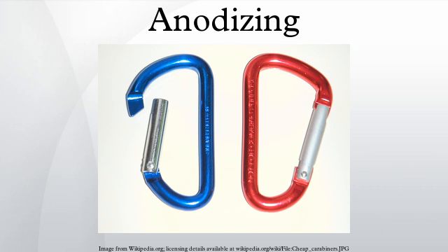Anodized coatings have a much lower thermal conductivity and coefficient of linear expansion than aluminium. As a result, the coating will crack from thermal stress if exposed to temperatures above 80 degrees Celsius. The coating can crack, but it will not peel. The melting point of aluminium oxide is 2050 degrees Celsius, much higher than pure aluminium's 658 degrees Celsius. This and the non-conductivity of aluminium oxide can make welding more difficult.